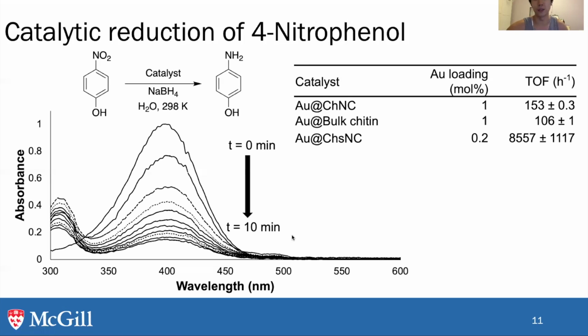Then we looked at using gold on chitosan nanocrystal. This is where we see almost 2 orders of magnitude difference, even at lower gold loading. So in this case, we can really attribute the amine functionality to binding and creating a more highly dispersed gold system on our chitosan nanocrystal. And again, we compare this with bulk chitosan, where we can see that yes, it is still higher than bulk chitin, but the nanoscale chitosan is so much more dominant than the bulk.